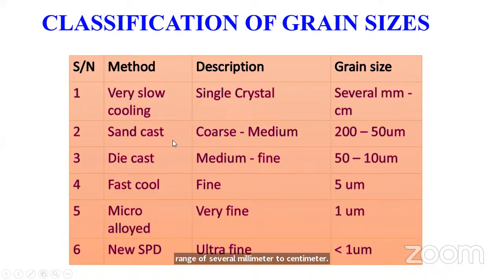If you go for a sand casting technique, where the cooling rate is somewhat medium, we obtain a coarse to medium grain structure, with grain size in the range of 200 to 50 micrometers. If you go for die casting, a medium fine grain structure is obtained, in the range of 50 to 10 micrometers grain size. And if you are cooling it fast, we get a finer grain size, ranging from 5 micrometers.